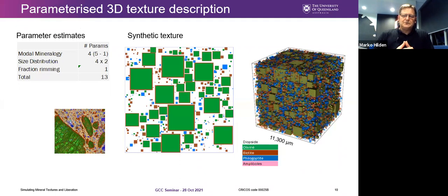So the model I've developed makes a 3D model of a texture using just simple parameters. Firstly, the modal mineralogy, i.e. the grade. So if we have a 5-phase texture, which we've simplified from this image, there's basically 4 degrees of freedom, and grade can be measured or estimated. Then there's the grain size distribution. There are several 2-parameter PSD models, and Rosin-Rammler, for example, is as good as any. So for 4 mineral phases, that's another 8 parameters, which also can be measured or estimated.